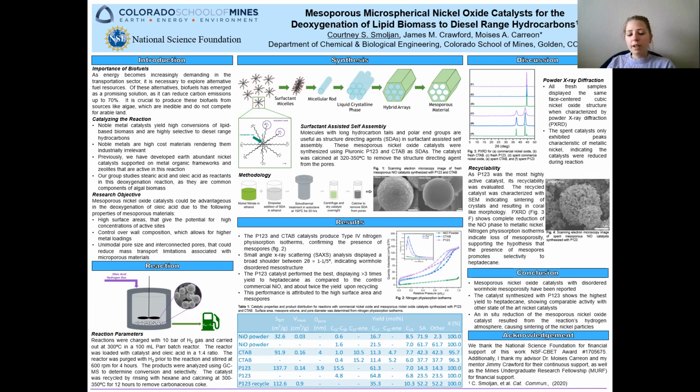We confirmed that we made a mesoporous material through nitrogen physisorption isotherms, as you can see in the results section here. We know that we made nickel oxide from our powder X-ray diffraction. We tested the recyclability of our catalyst also, and you see some sintering of the crystals.